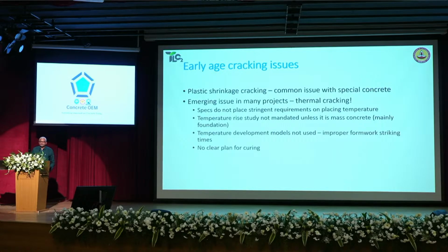An emerging issue is thermal cracking. One, again, specs don't place stringent requirement on the placing temperature. Temperature rise study is not mandated unless you're doing a mass concrete like a dam or a massive raft. But these days, many of the columns and shear walls in high-rise buildings and all our viaducts, these are all actually classified as mass concrete because they are 2 meters thick, 3 meters thick, and so on, right? And temperature development models are not used, and very often these models are necessary to understand when do I remove my formwork.